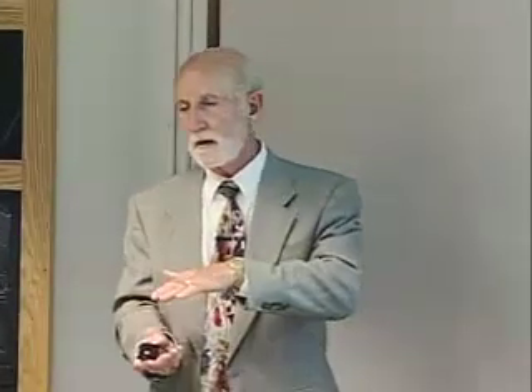I'm going to skip forward here and show you one thing. This allowable over here, let me see if I can see it. That's 50 thousandths of an inch. The ultimate for the tile was 12 psi, basically a little bit less than 12 psi. So that means the ultimate stress was 12 psi. The allowable stress was about 8 psi, and that's with the total loads combined on the tile.